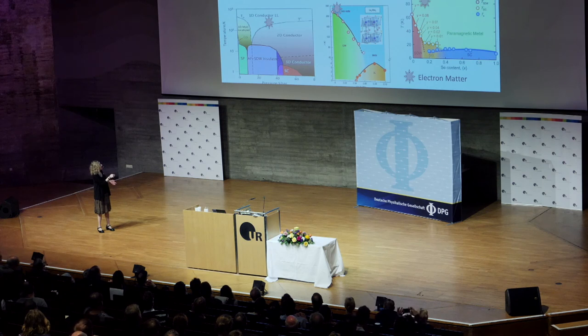The cuprates have the same kind of phase diagram. We have a Fermi liquid here, and a strange metal here. The iron-based superconductors, I've studied both of these a good deal. Here we have magnetic order, out here is Fermi liquid, superconductivity under the dome. We have superconductivity in organics, and these are the transition metal dichalcogenides, which were also found a few years ago to have that. Here's another iron-based superconductor. It's fascinating. I should have put my 115s up there.